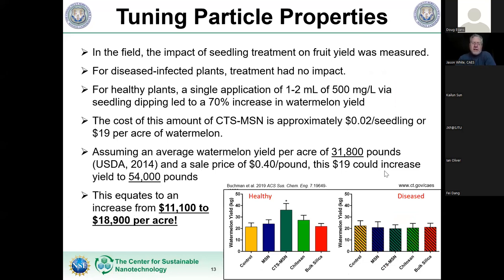This study had a field component where the silica treatments had no impact on disease in field conditions — a case where greenhouse results didn't translate. However, in healthy conditions, our chitosan-coated mesoporous silica increased yield by 70%, representing a $19 per acre investment that produced 20,000 more pounds of food — or about $7,000 to $8,000 per acre — simply by supplying a nutrient the plant needs but can't get enough of.